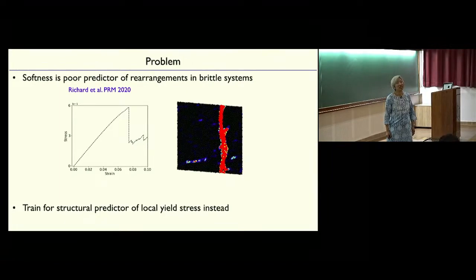So I was wondering what sets localized versus distributed plasticity. In the last example, is it the capillary length? So if the particle size is below the capillary length, you get distributed plasticity. Well, it's the ratio. People have found that if you change the range of attraction and make it smaller and smaller, you get more and more strain localization. They don't understand why, but this is an empirical finding.